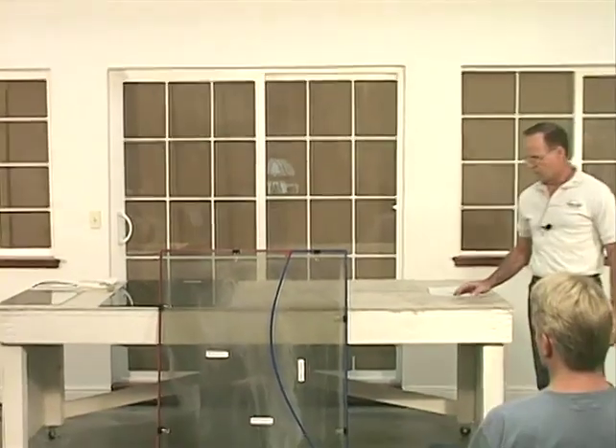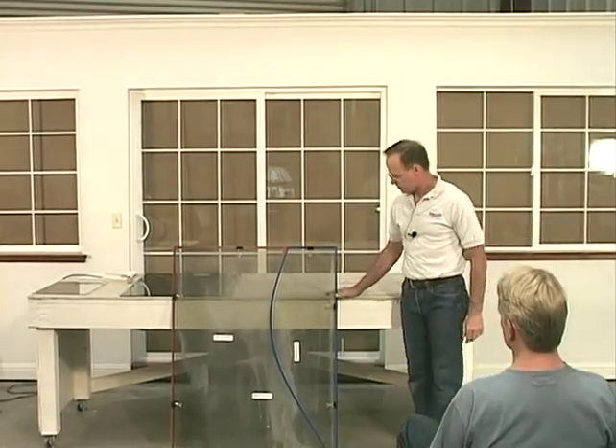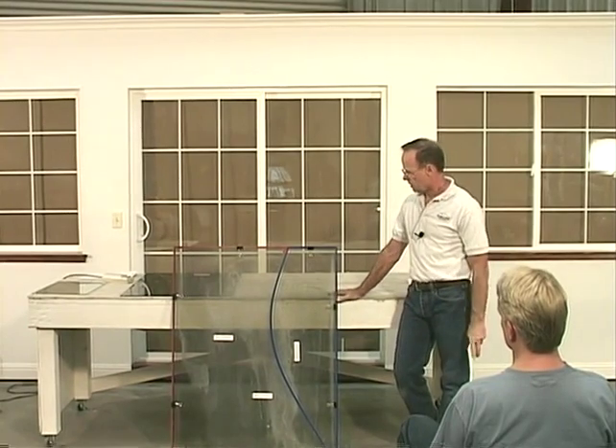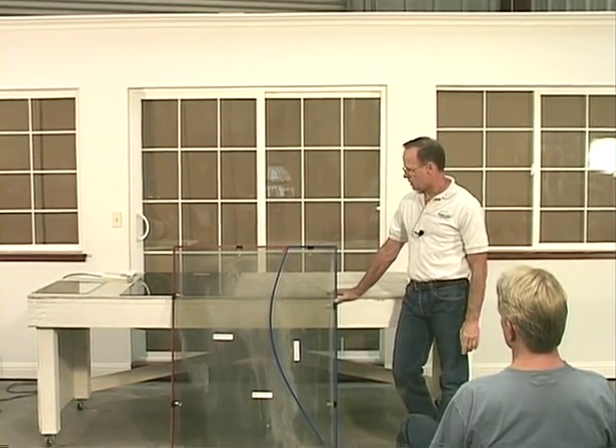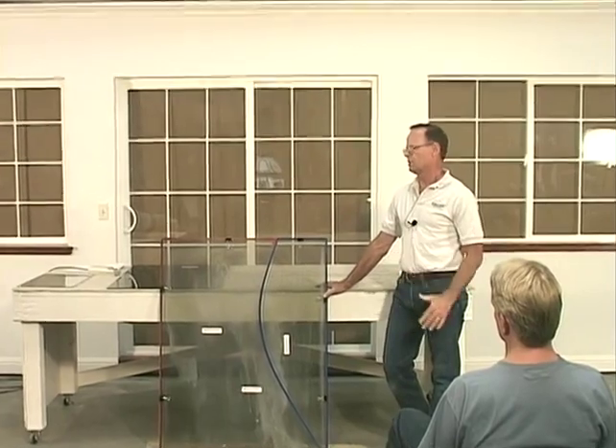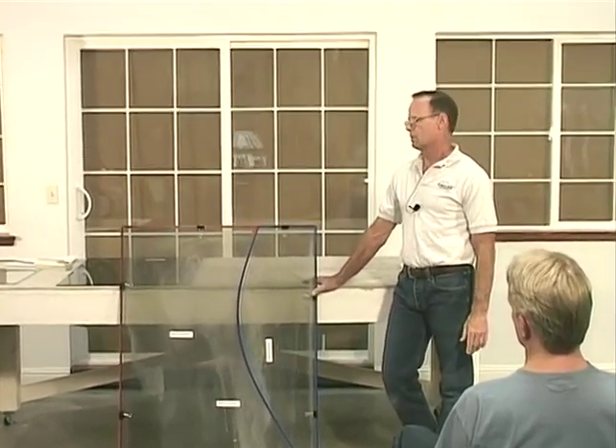Where you will see glass corrosion is in two main areas. One area will be on an IG unit. If you have a seal fail on an IG unit, what will happen is moisture will get in between the glass, and it will actually corrode the glass. In fact, I have a sample here that I will show. This here is actually true glass corrosion, and we'll have some photos of this also. But actual glass corrosion is actually corroding the surface of glass. This is moisture-induced glass corrosion.